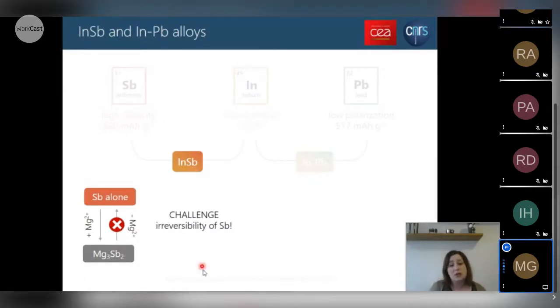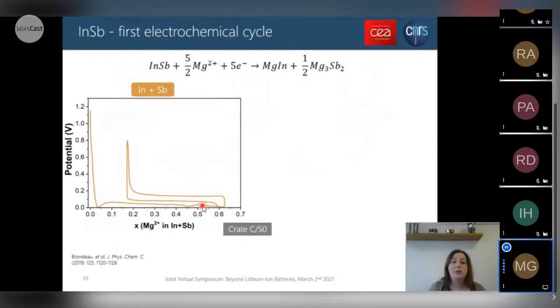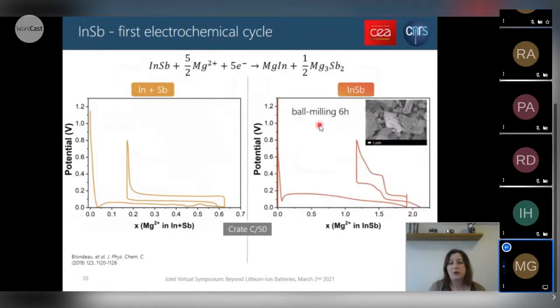One thing that needs to be noted is that here the main challenge is in fact the irreversibility of antimony. If you look at the reactivity of antimony alone with magnesium, it is able to react with magnesium to form the Mg3Sb2 phase. But this phase is really stable, and the reverse reaction extracting magnesium from this structure is almost impossible. So this is the challenge we have to tackle here in the InSb intermetallic compound. First, to determine if a synergy exists between indium and antimony in the InSb alloy, we compare a simple mix of indium and antimony with an InSb compound that we produce through ball milling.